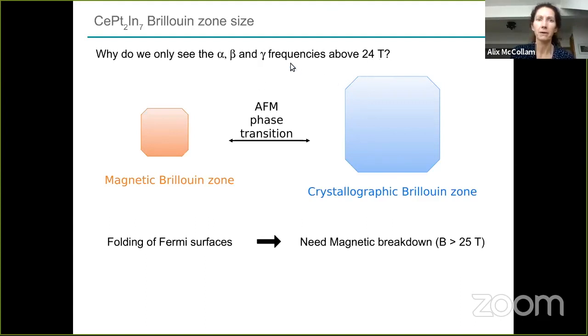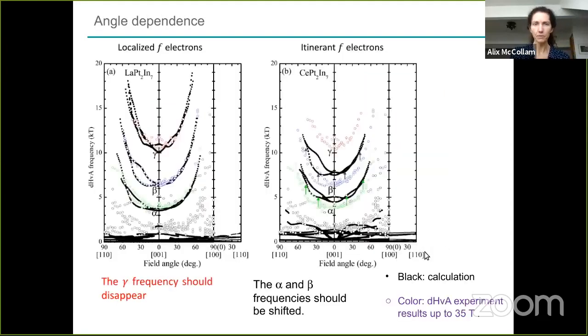And this corresponds very well, but we see these frequencies start to appear above 24 Tesla. So we're seeing them in the antiferromagnetic state because of magnetic breakdown that occurs above 25 Tesla. So this is a comparison of the angle dependence of the de Haas-van Alphen frequency.